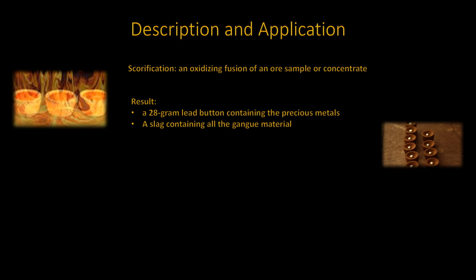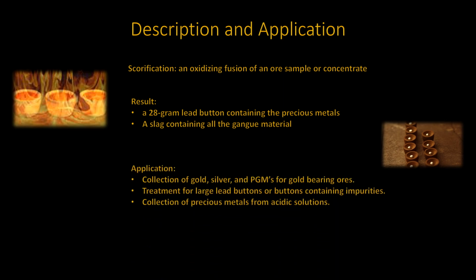Scorification is the simplest and may be the cheapest method for collecting gold and silver from your ore samples or concentrates. This may include some of the platinum group metals as well. During a crucible fusion process, your resulting lead buttons may be too large, or they may be too contaminated for cupellation. Scorification can be used to further reduce the lead by removing or trapping the contaminants in the resulting slag. If you have any solutions containing gold or silver, scorification can be used as a method of collection and separation, a wet-dry process.